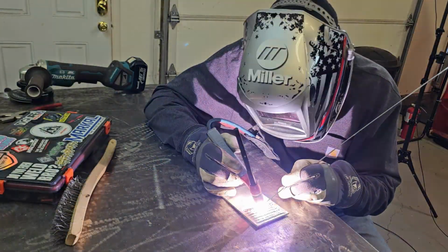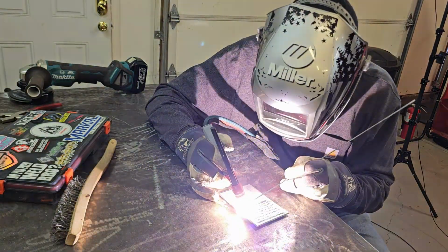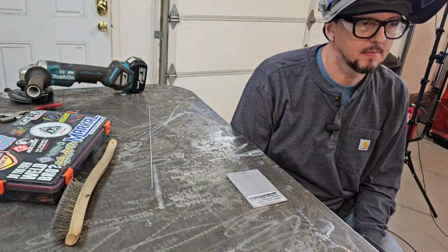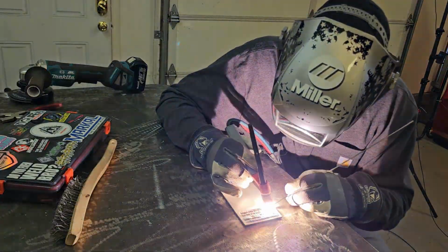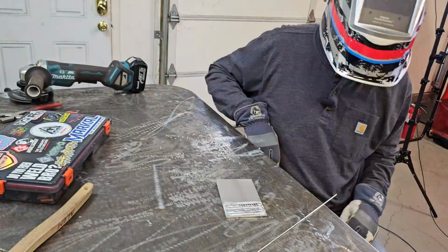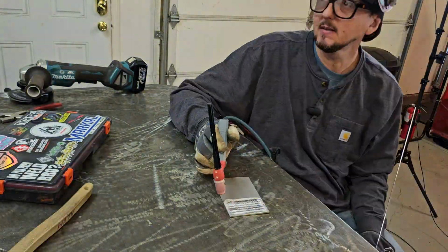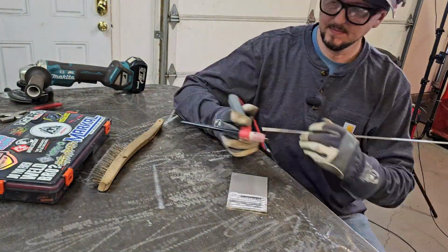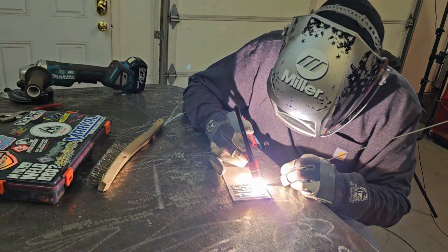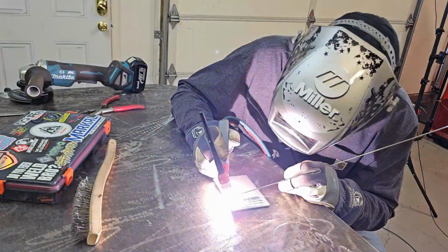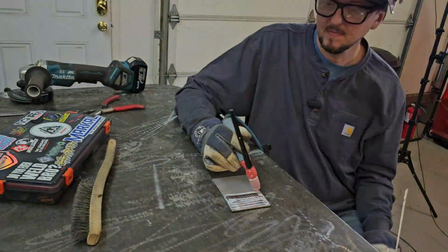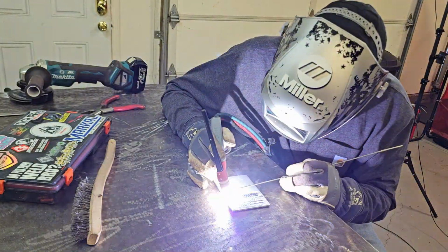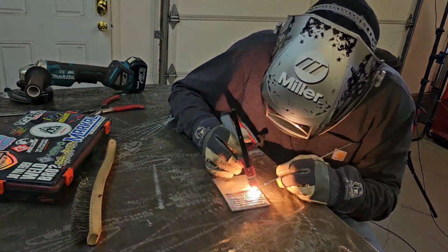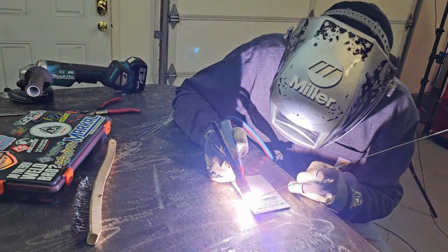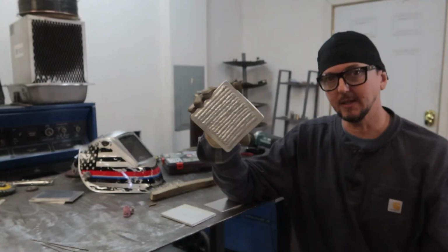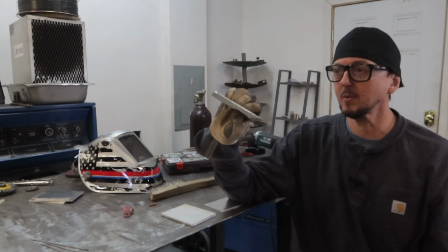And by the time we get done with this, our speed and our efficiency and our quality will be a lot better than when we started out. This is what I did when I first started welding aluminum, and it really built my speed and my ability to move the filler through my filler rod hand. Overall, I got a lot of arc time on this one piece of material, and it improved my skill pretty quickly. So that's what we're going to do today.